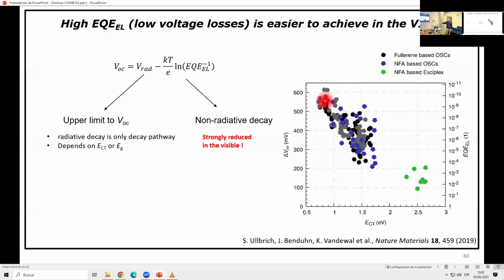We thought, okay, if this is really true, this is all the solar cell materials we could find. Let's do something very unconventional that nobody would do. Let's just take two donor and acceptor materials, but with band gaps at higher energies. Mix the two, the CT state energy is still at high energy, so they're visible light. So for solar cells, they're not good. Why are they not good? Because the gap is high and they don't absorb much light. But we wanted to check the voltage and the voltage losses in particular. Is this good then? And that's very good.